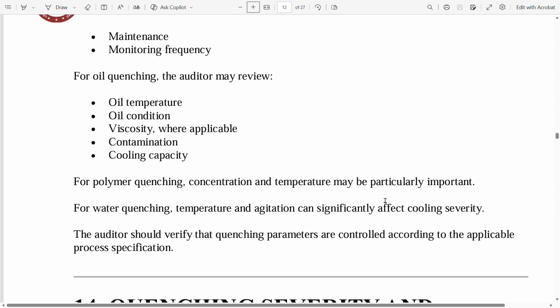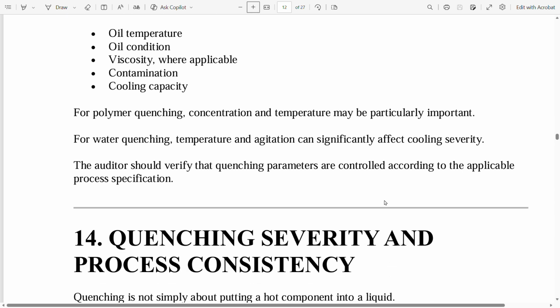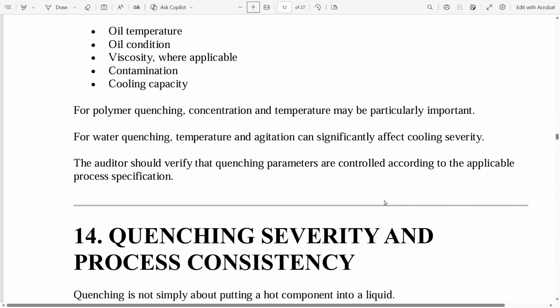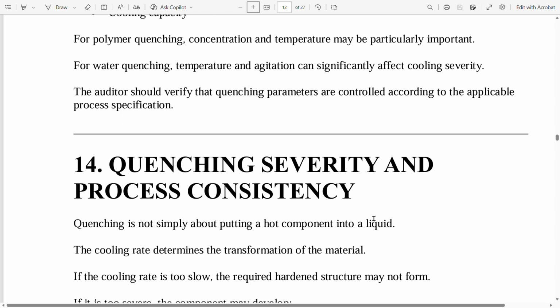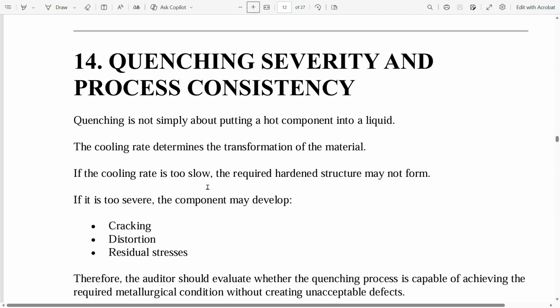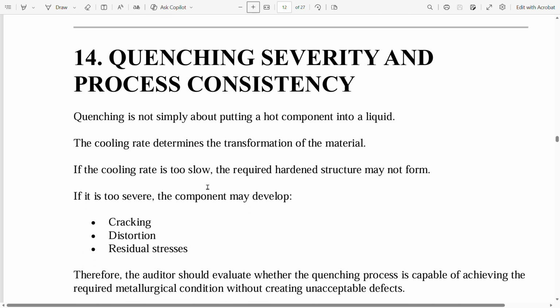For polymer quenching, concentration and temperature may be particularly important. For water quenching, temperature and agitation can significantly affect cooling severity. The auditor should verify that quenching parameters are controlled according to the applicable process specification. And next is quenching severity and process consistency.